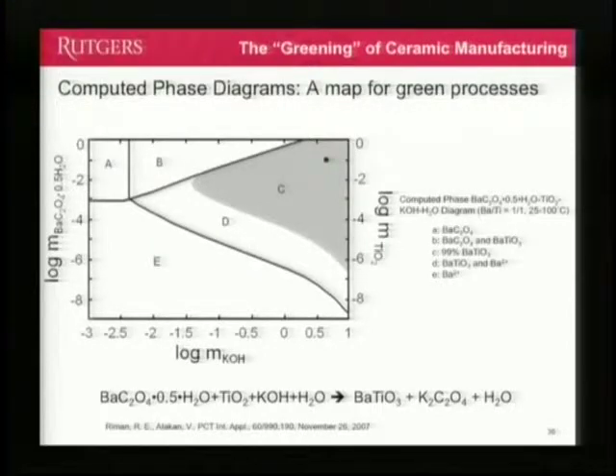So the way we start is calculating a phase diagram using thermodynamic principles. And so this shaded area here shows you where you need to run your reaction conditions in order to run this reaction, where we take an oxalate and we react it to form barium titanate. And this is actually an equivalent reaction. This is actually a single compound, but this is the only way we could model it. So this model told us if we add lots of KOH to the system, not only will we get barium titanate, but we won't release any CO2. And this is a room temperature diagram.